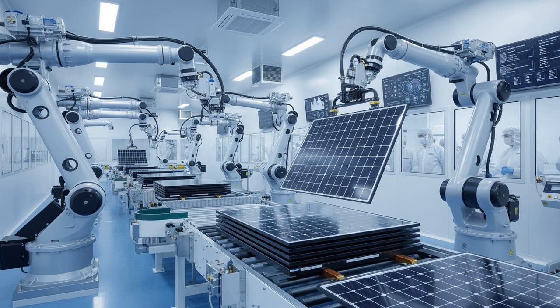Oxford PV, a spin-out from the University of Oxford and a pioneer in tandem cell commercialization, has been leading the charge in bringing this technology to the masses. In June 2024, Oxford PV debuted a residential-sized tandem solar module with an unprecedented, independently certified efficiency of 26.9%. While 26.9% is obviously lower than the 34.85% lab record, it is a monumental leap for a commercial-sized module. Traditional commercial silicon panels average around 20 to 22%.